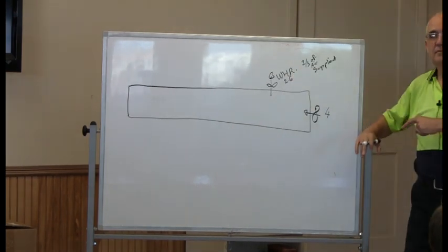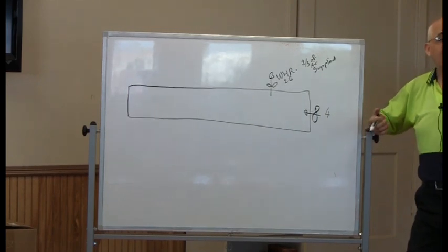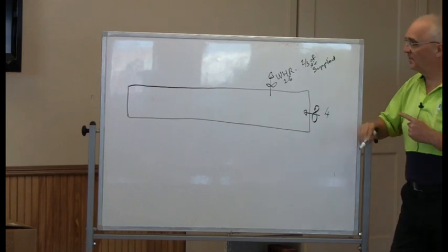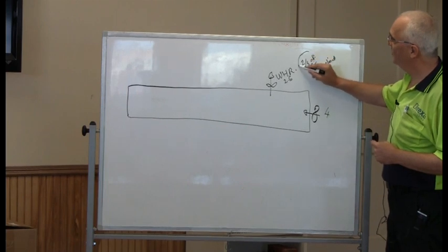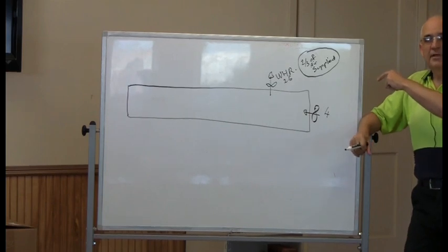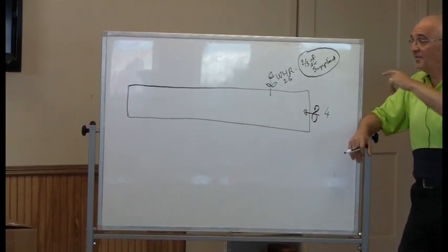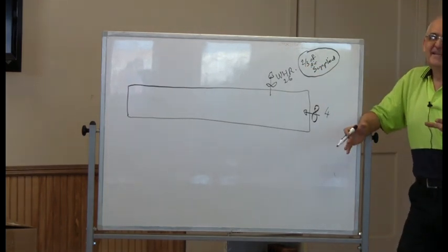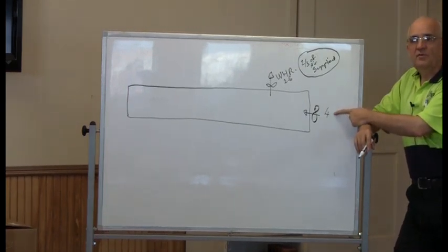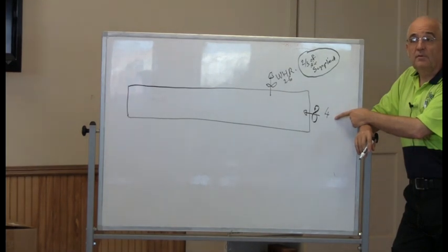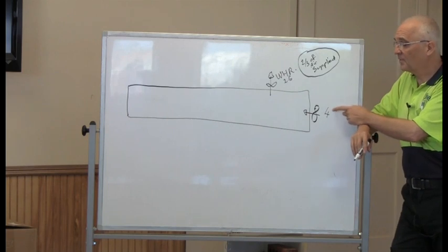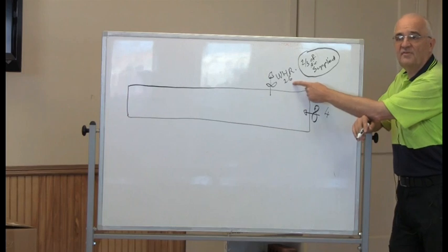But if I start with 2, well, I'll have 1.4 or something like that. So what is really important is to make sure that we are around that ratio. And that ratio of ratio is kind of universal. What is not universal is some kilns run with 3, some kilns run with 2. Okay, that's fine. If it works, that's fine. But what is important is if I'm down to 2 here, I can't be at 2.6 here.